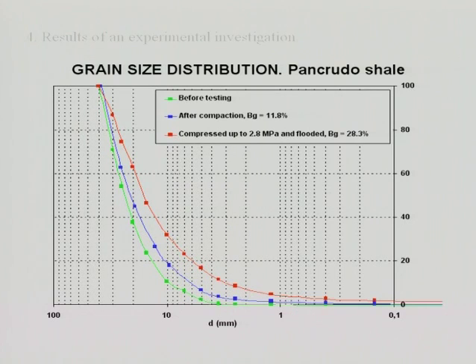You should measure the evolution of the grain size distributions just to know how the material breaks, and you can have a feeling of how this initial material, given by this green curve here, evolves, and you can also compute some coefficients that tell you what is the intensity of breaking. But clearly, after this type of testing, you compact and then you break some of the grains. Compression and flooding, etc., result in an increased proportion of smaller particles, and you can analyze this type of results.